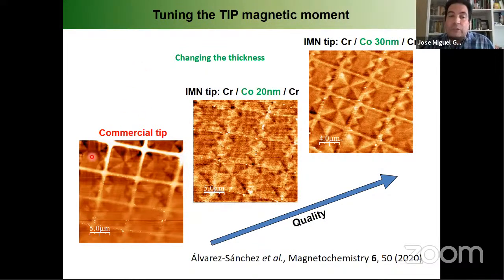In this case, what was happening was that the tip was being remagnetized by the sample stray field. You can see that they will send you tips with low coercivity or with high coercivity, low magnetic moment, high magnetic moment, but they are not so reproducible. My advice is that it's better if you can prepare your own tips, at least for challenging samples.